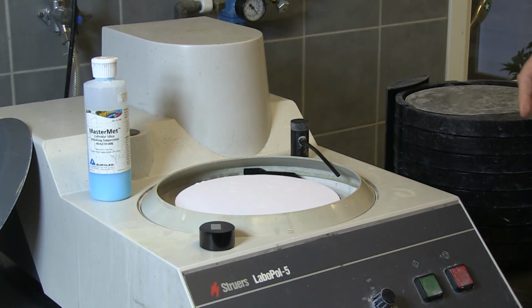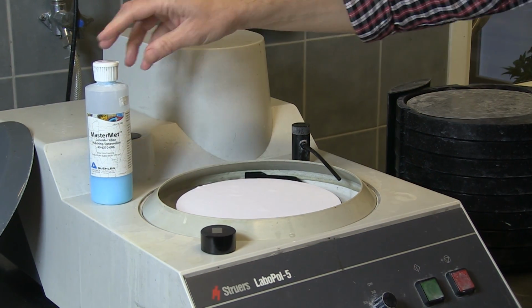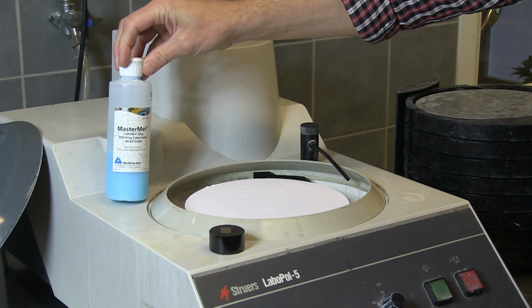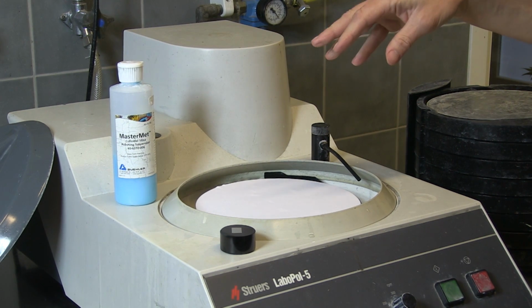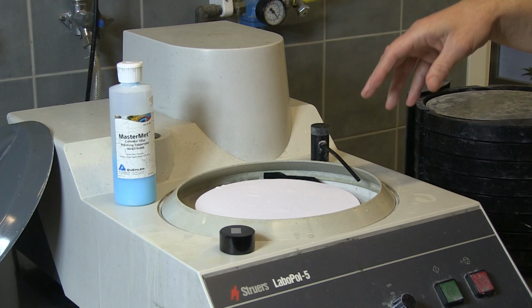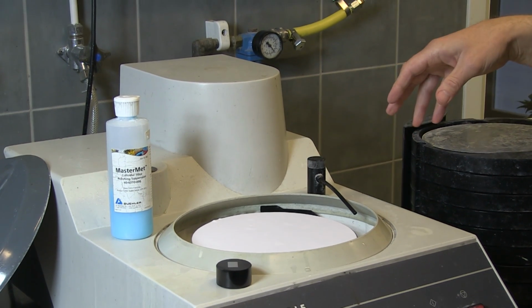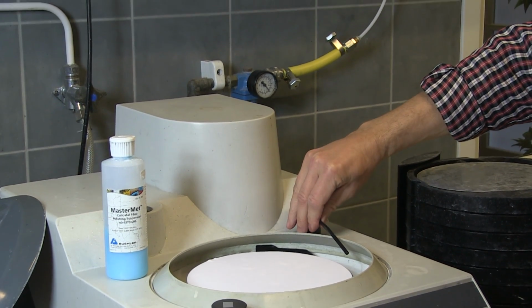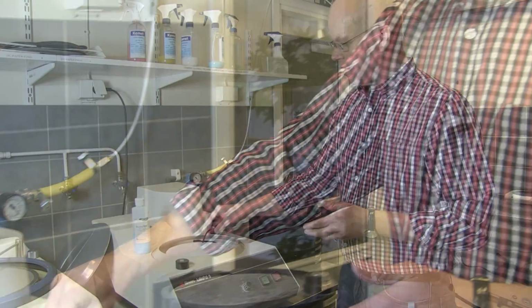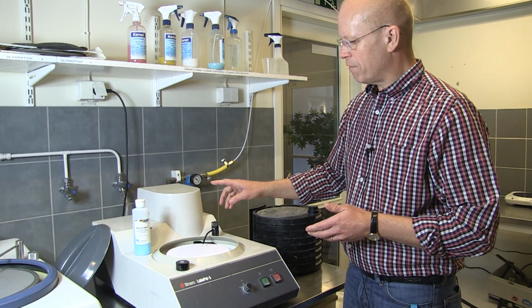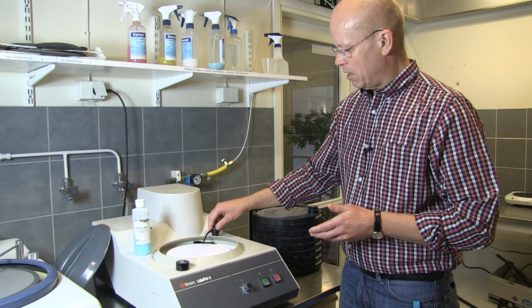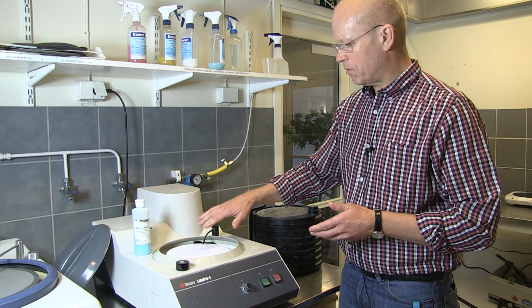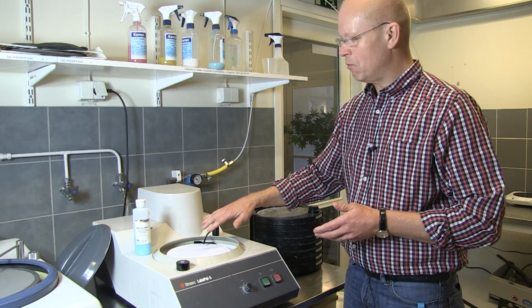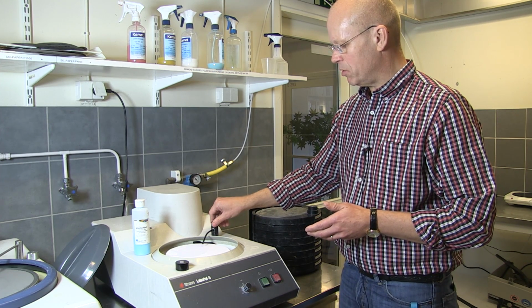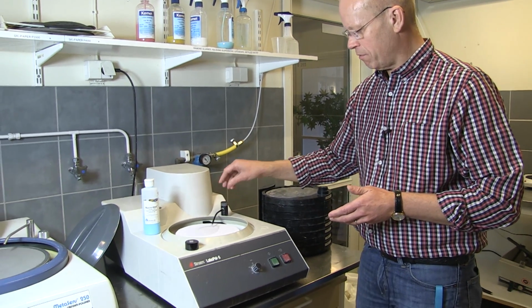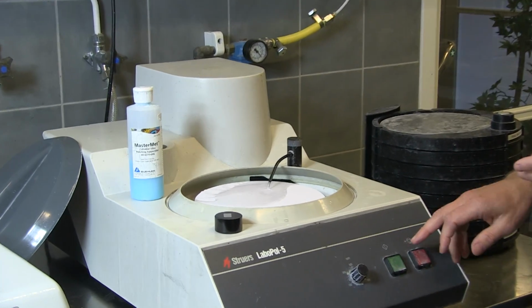And when you use a final polishing cloth and a final polishing suspension such as that one, you should always do it on a pre-wet cloth, preferably with distilled water. I don't have any distilled water here, and as a matter of fact the Luleå river water works pretty good anyway. Always during final polishing sequences you should start with a cloth that is pre-wet, preferably with distilled water. I don't have it at the moment, so I will use tap water. It works pretty good as a matter of fact, but preferably distilled water.